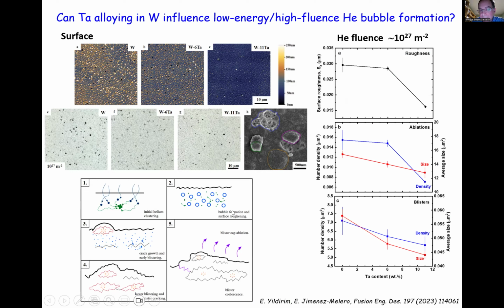So what we think happens is that helium, if you look at sketch number 1, helium goes a few nanometers into the surface of tungsten, diffuses, agglomerates, forms small clusters, then small bubbles. Those bubbles start to agglomerate and they form blisters, and at some point the blisters just have so much local strain that they actually eject material and cause ablations on the surface. So what we think is that by putting a little bit of tantalum, it delays the helium diffusivity, before they form the small bubbles and the blisters.